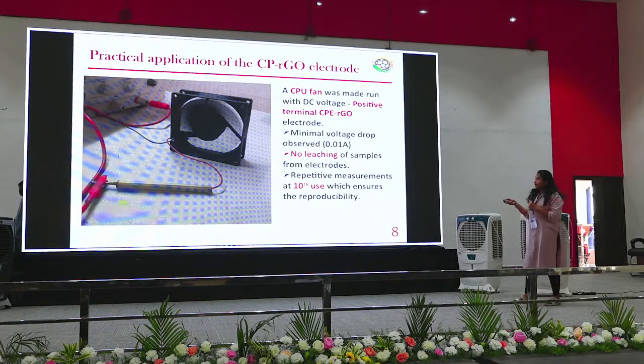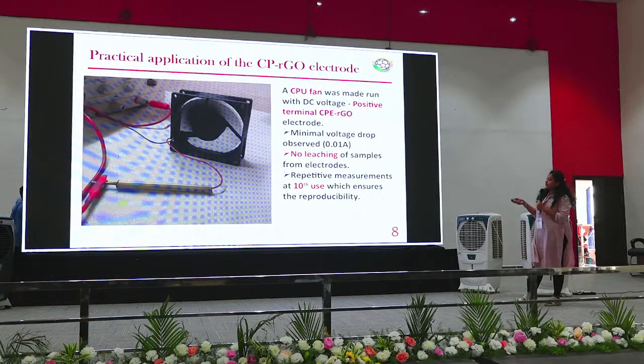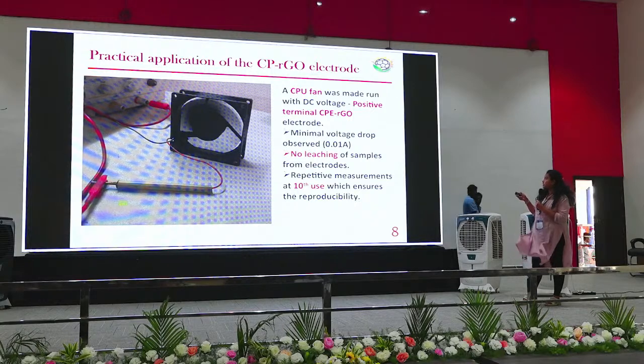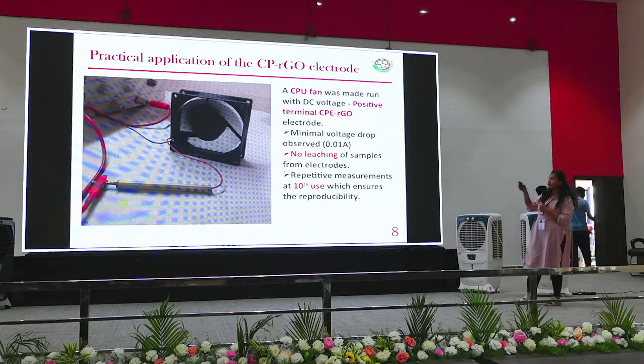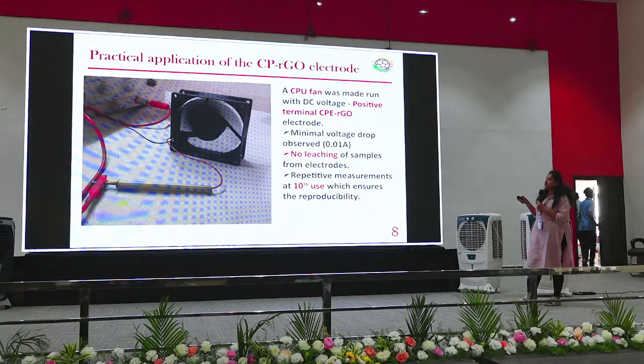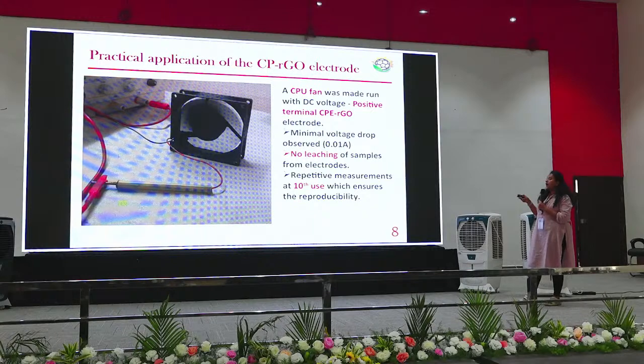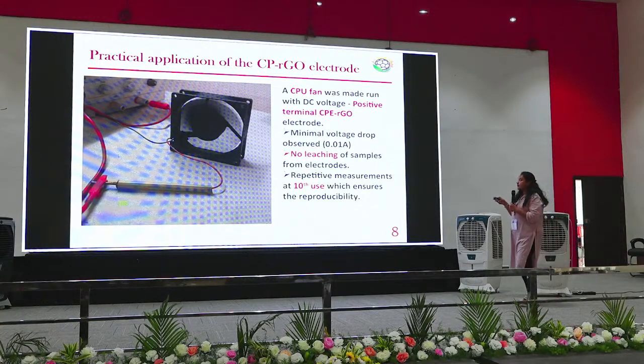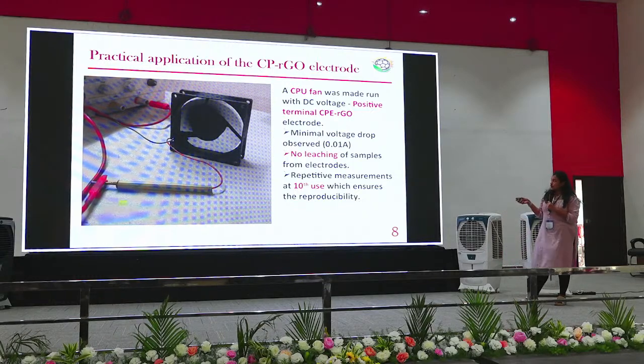For the practical application, we incorporated the RGO electrodes and ran a CPU fan with a DC voltage, with the electrode kept as the positive terminal. We observed minimal voltage drop, and it ran for 10 minutes, and there was no leaching out of samples. Even for the 10th use, repetitive measurements were obtained, which shows the reproducibility of the electrode.